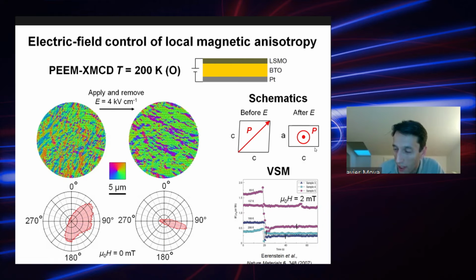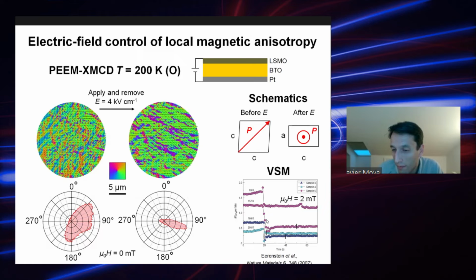So in this case will be the z-axis. And this is why you have this kind of uniaxial magnetic anisotropy of the electric field. This is consistent with early observations done using only macroscopic magnetization data, where it was reported that when applying field at this temperature, the magnetization was dropping significantly.